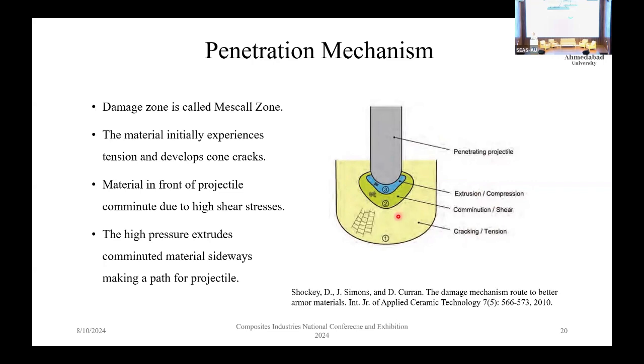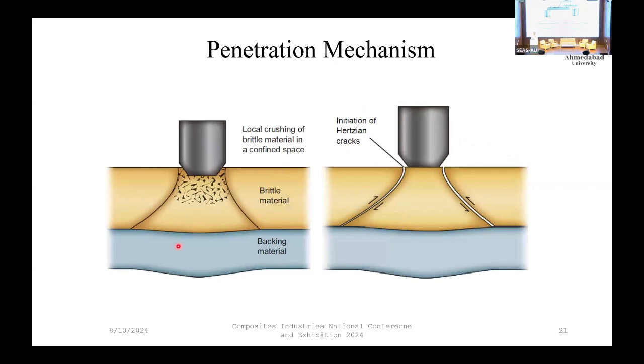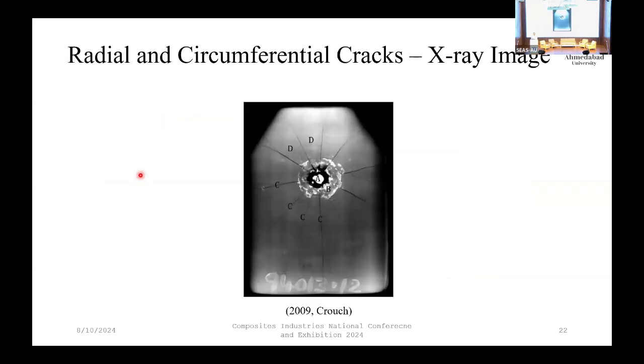So at the back of that, we will place a backing material, and that backing material can be ultra high molecular weight polyethylene. And this is how a crack will grow like this. So here we can see that there is a bending phenomenon. Part of the material is trying to remain there and a part is being pushed. So a specific type of cone will be created depending on the composition and the processing we have done with the ceramics. And in turn, the tip of the bullet will perform the grinding or pulverization of the material in front of it.